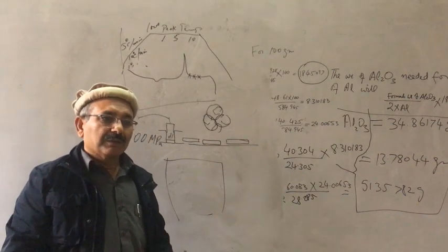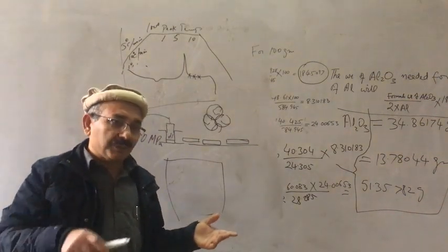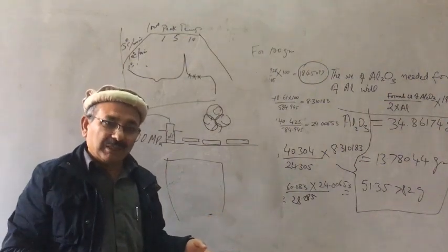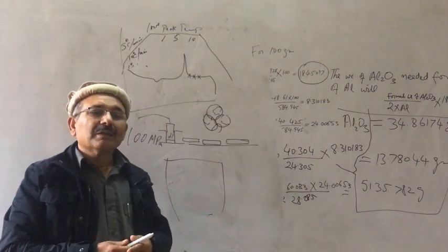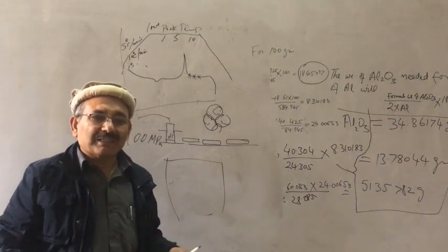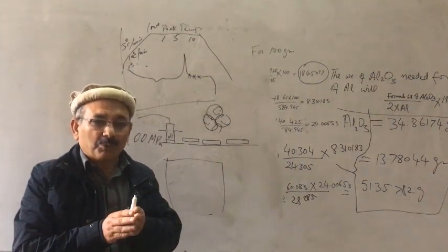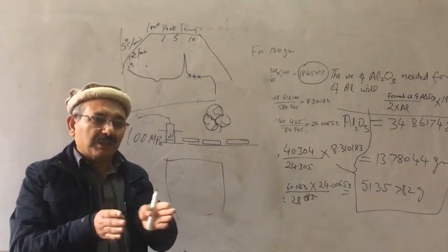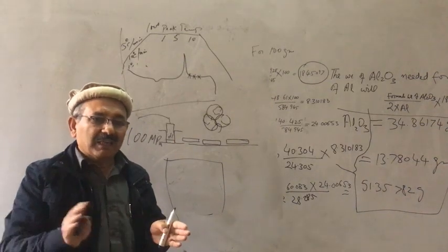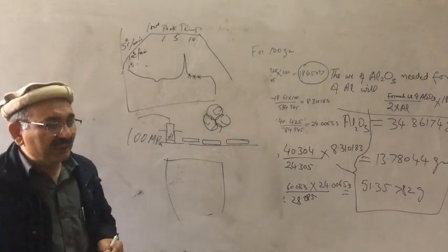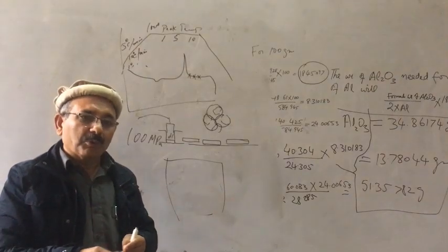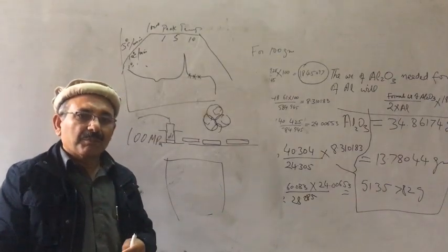You are making a toroidal core, for example, so you need a hole in the middle of the pellet. You need to measure, for example, the dielectric constant, so it should have electrodes. Put electrodes on both the smooth surfaces, polish the surface so that it is clean, then put gold paste, silver paste, palladium paste.